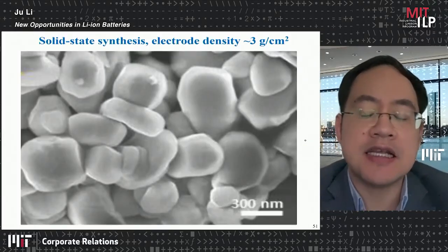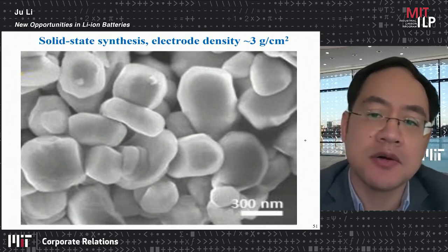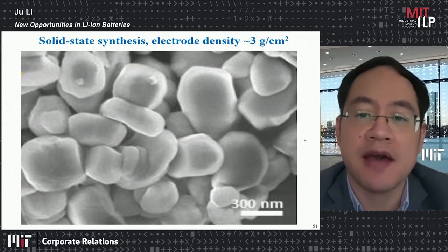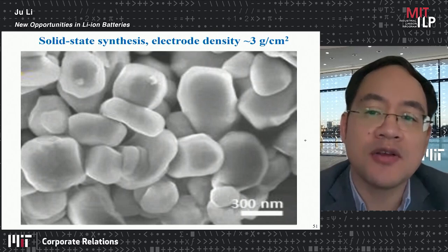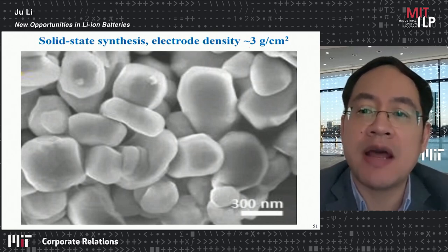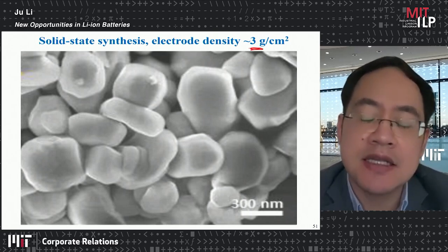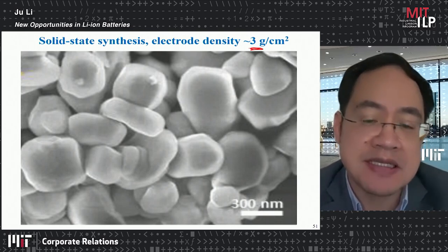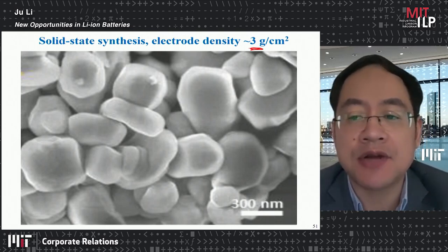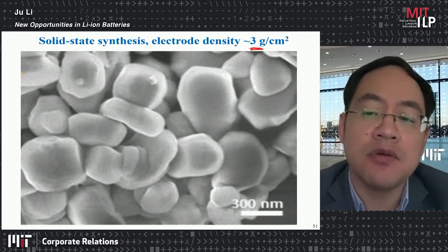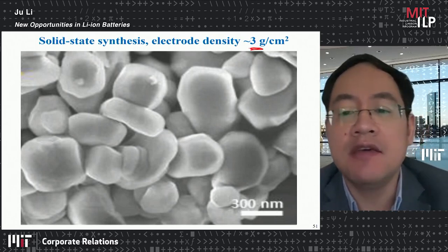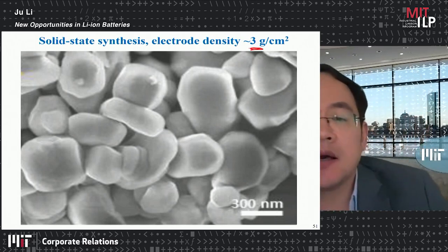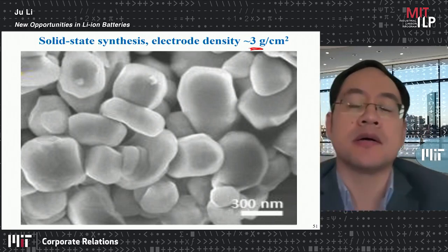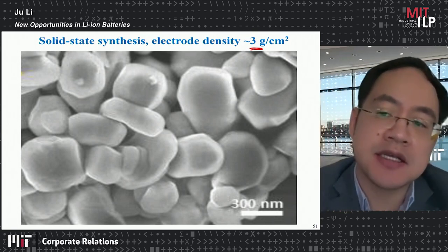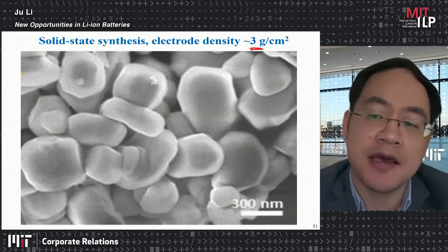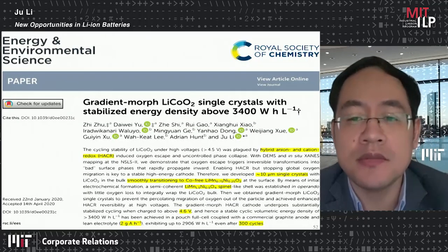And finally, these are the morphologies of the particles. So we don't have secondary particles. We have these round cornered primary particles, and compressed density is already close to 3 gram per cc. So it's actually already have a pretty decent volumetric energy density. So even at 200 cycles, the cathode energy density is close to 850 watt hour per kilogram.